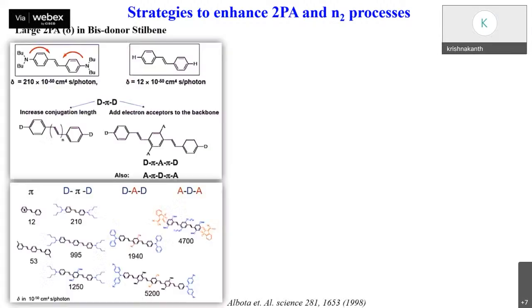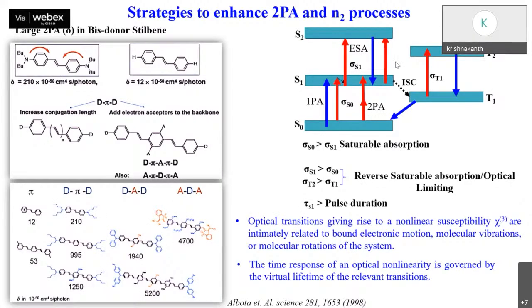As my thesis title suggests, we used organic and inorganic molecules. In the case of organic molecules with donor-pi-acceptor or donor-pi-donor structure, these molecules have strong NLO activity, with several studies reporting values of the order of 210 GM units. The right side shows the Jablonski diagram, which represents the different transitions that mostly participate in this nonlinear absorption, where sigma is the cross section. If sigma S0 is greater, you have saturable absorption. If sigma S1 is greater than sigma ground state, you have reverse saturable absorption and optical limiting properties.